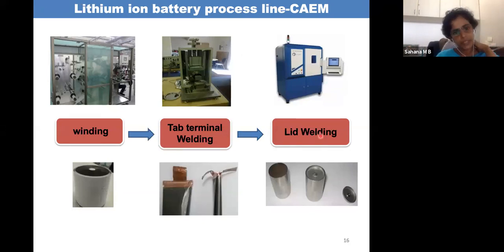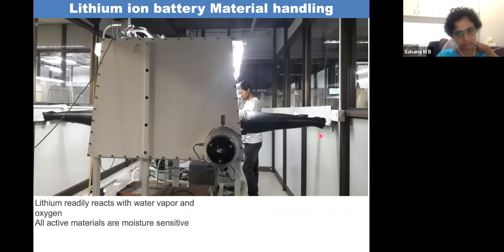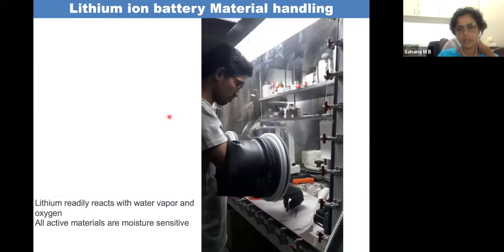But every material we study, we cannot make an 18650 cell or the full cell in a pilot plant, which requires around 1 to 2 kgs of material for every batch. So we need to do it in a smaller cell, which I'll come to, the cells we study at a smaller level. Those things are done using a glove box, where the oxygen and the moisture level in this box is controlled to less than approximately 1%. So the smaller level electrode coatings and the cells are fabricated in the glove box.